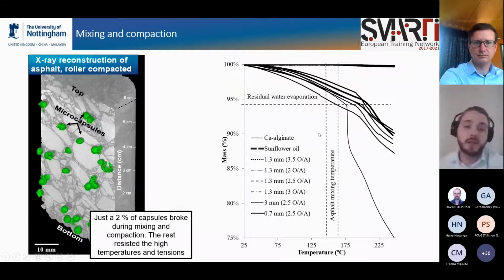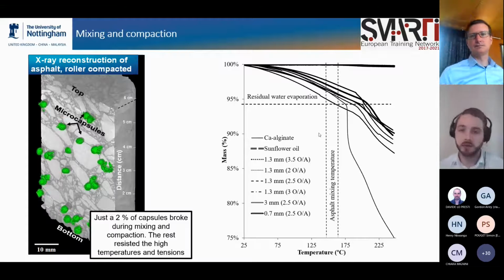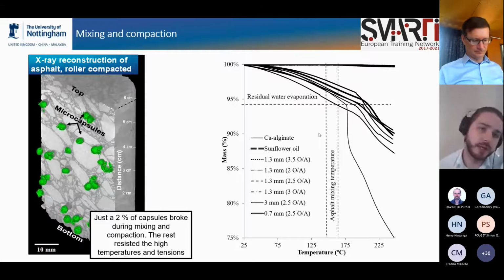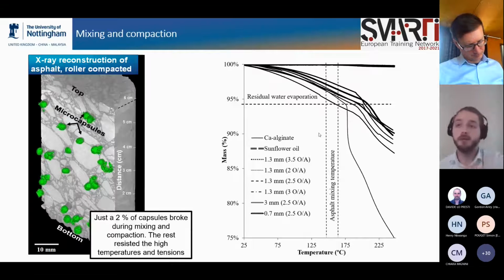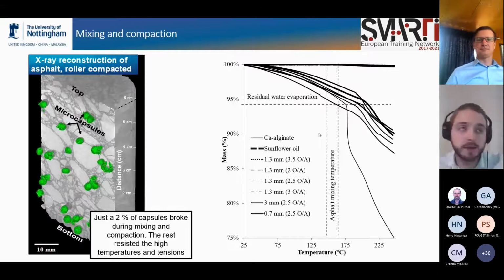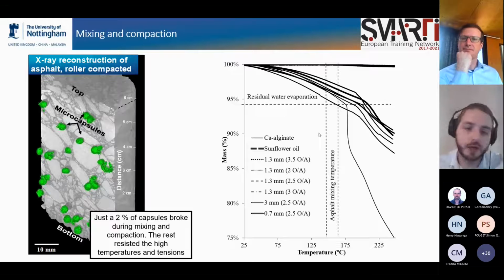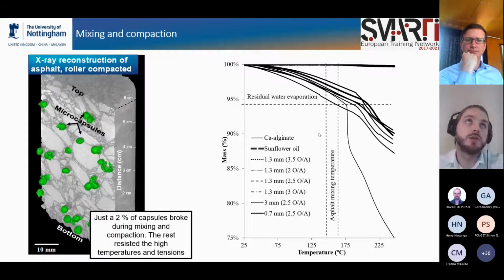Okay, yeah. So the first question we needed to answer was: are the capsules able to resist the compaction and the mixing process of the asphalt? For that, we did an X-ray reconstruction of the asphalt after being compacted, and we observed that some capsules were broken during this process, as you can see in this image. But this was just around 2% of the capsules that showed obvious damage.